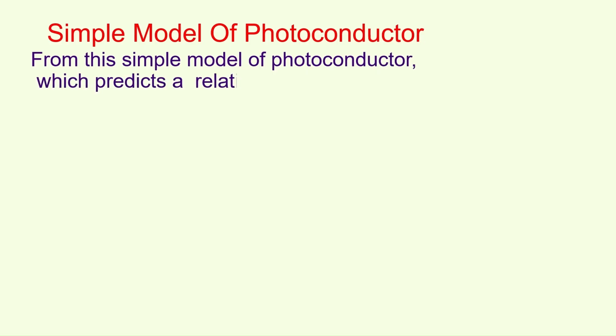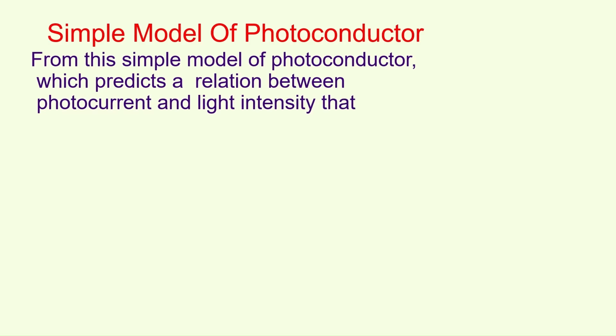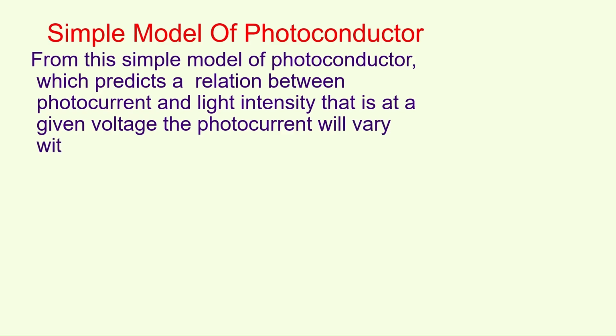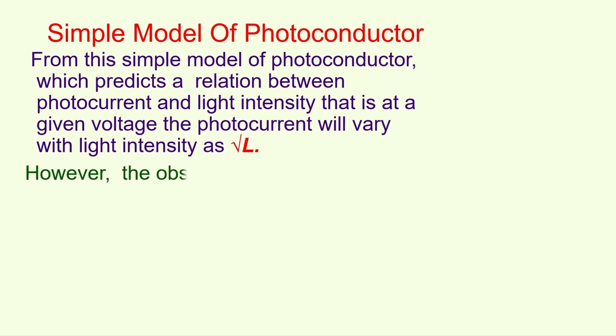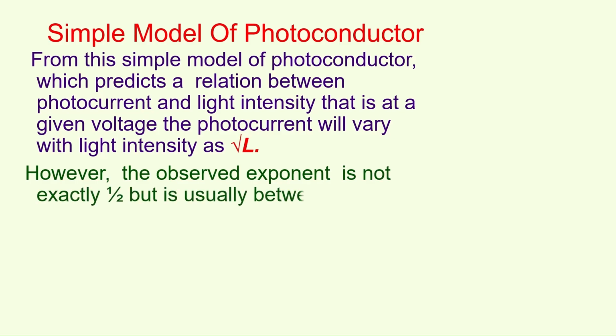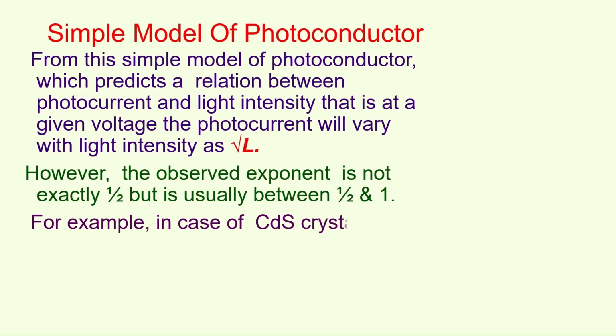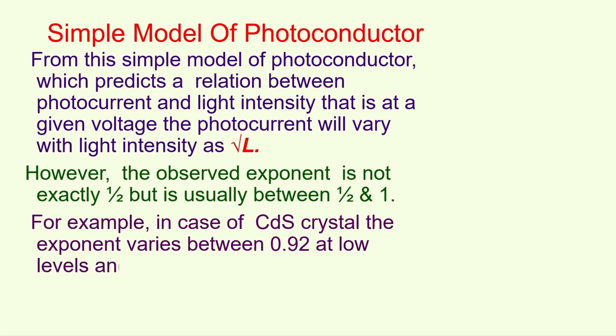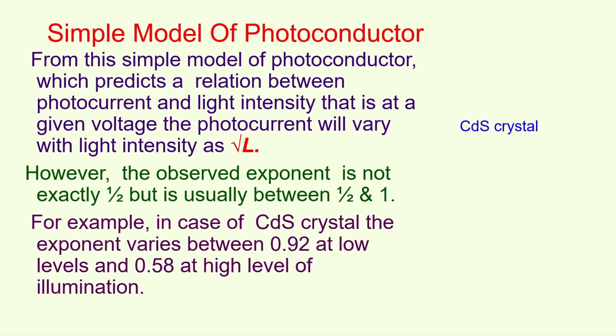This simple model of a photoconductor predicts a relation between photocurrent and light intensity, that is, at a given voltage, the photocurrent will vary with light intensity as the square root of L. However, the observed exponent is not exactly half, but is usually between half and 1. For example, in the case of a cadmium sulfide, CdS, crystal, the exponent varies between 0.92 at low levels and 0.58 at high levels of illumination.